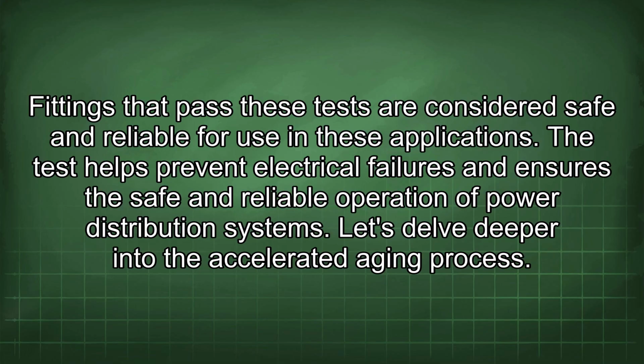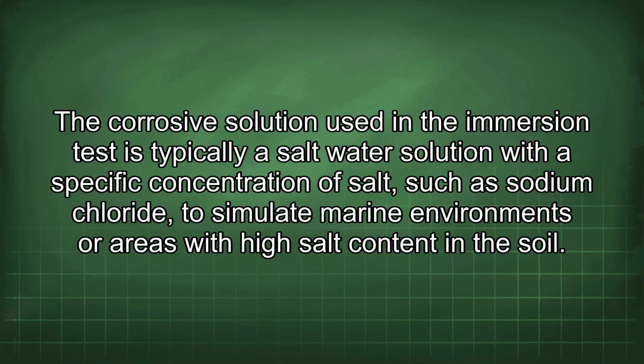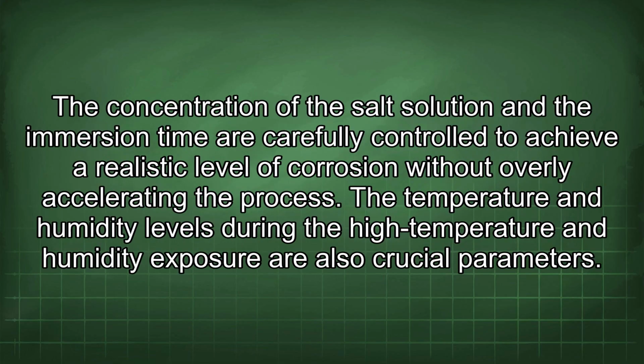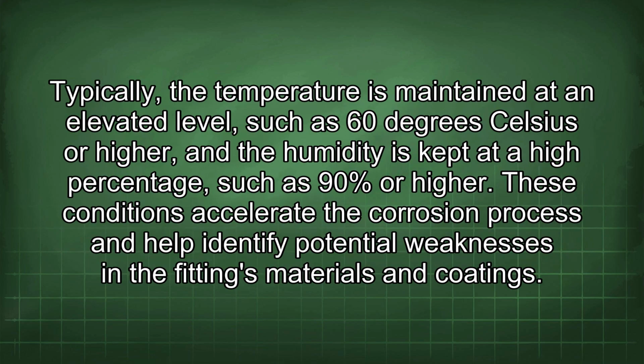Let's delve deeper into the accelerated aging process. The corrosive solution used in the immersion test is typically a salt water solution with a specific concentration of salt, such as sodium chloride, to simulate marine environments or areas with high salt content in the soil. The concentration of the salt solution and the immersion time are carefully controlled to achieve a realistic level of corrosion without overly accelerating the process. The temperature and humidity levels during the high temperature and humidity exposure are also crucial parameters. Typically, the temperature is maintained at an elevated level, such as 60 degrees Celsius or higher, and the humidity is kept at a high percentage, such as 90% or higher. These conditions accelerate the corrosion process and help identify potential weaknesses in the fittings, materials, and coatings.